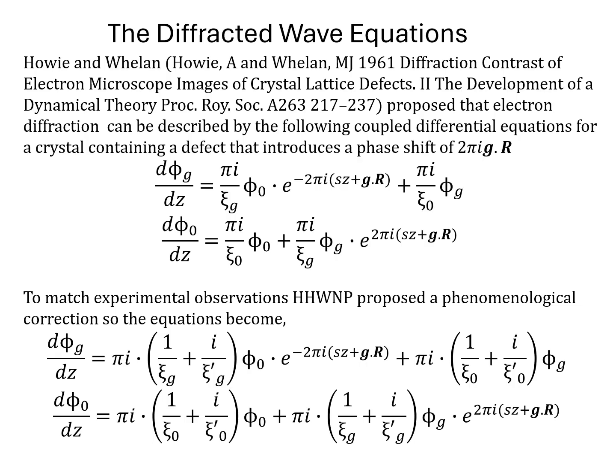In an electron microscope, in a material with electron diffraction, it's slightly different because, well, it's a lot different because the electrons interact so strongly with the crystal that when they're diffracted, they can all then rediffract and then interfere with the direct beam. So what actually happens is that you end up with a coupling of the diffracted wave and the direct wave.